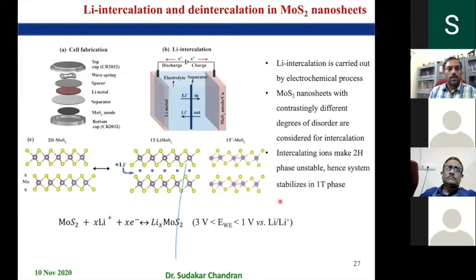Here in this slide, I will show another way of manipulating the magnetic property in the molybdenum disulfide nanosheets. So what we did, we took the same molybdenum disulfide as I discussed in the previous slides, and we took it as one of the electrodes, and then put it as a lithium half cell with the lithium metal as an anode, and then did the intercalation.